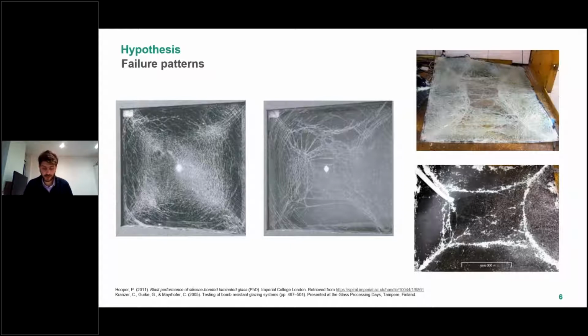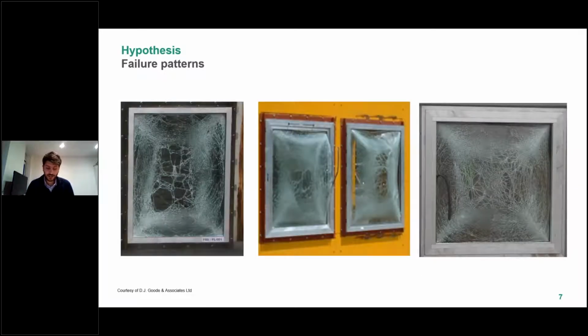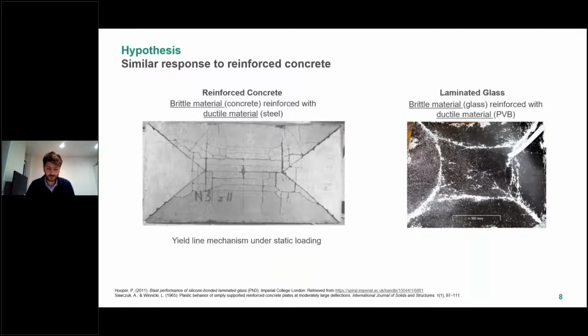The starting point in my research was to study the failure mechanisms in laminated glass recorded by previous researchers during full-scale blast tests. I observed a repeated failure pattern that was consistent in almost all tests. This failure pattern resembles the yield line mechanism forming under bending in reinforced concrete slabs. Given the similarities between laminated glass and reinforced concrete, that is, both are brittle materials reinforced with a ductile material, I decided to investigate if this repeated failure pattern in laminated glass is in fact a yield line pattern.